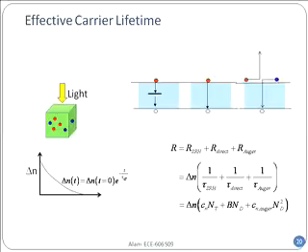Oh, yes, it depends on the number of dopant atoms, but as a square, because two of them have to bump against each other. So they have different dependencies. If I do a set of experiments in which I change the dopant level systematically, then this decay will be different for each one of them. And from that, I should be able to pick out what these different coefficients are. You see?